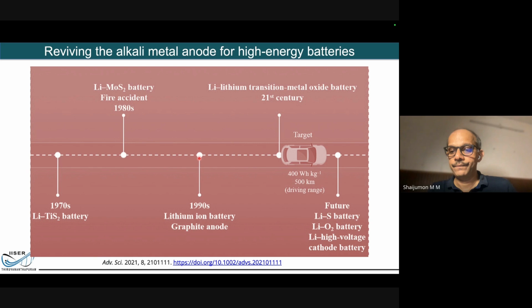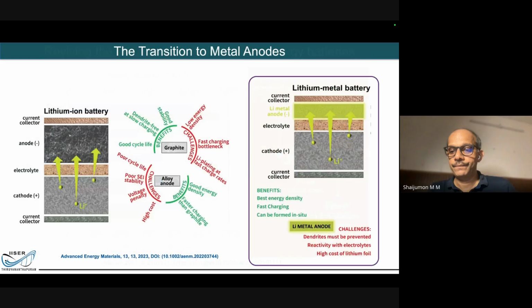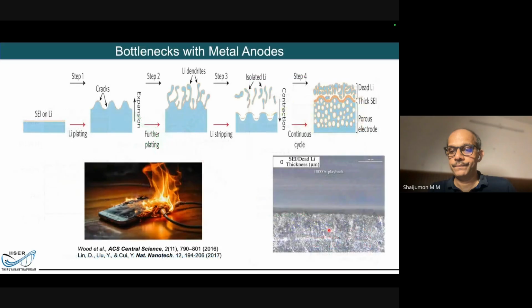So nothing new, but looking at the various new systems that are coming up, you need a high energy density anode material, and lithium is the best choice. But the problem is, the moment I use lithium, there are issues. For example, let's say these blue ones that you see here are the lithium metal anode. If I use lithium metal here, there is something called a solid electrolyte interface. It's an interface formed by decomposition of my electrolyte, a thin film that basically protects the lithium. So what happens is the following.